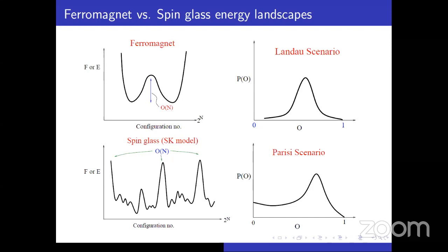Yeah, so this is the thing. Now, I am still on that slide, ferromagnet versus spin glass energy landscape, and you can see that to get the ground state in a ferromagnet kind of situation, you just change the configuration locally, say the spin configurations, and if the energy is lower, you just accept it, and you will hit the ground state. But in the spin glass phase, you will not be able to do that. You will come to a local minimum, and then the energy will only increase. Now, if you throw away higher energies, then you are not going to go anywhere.